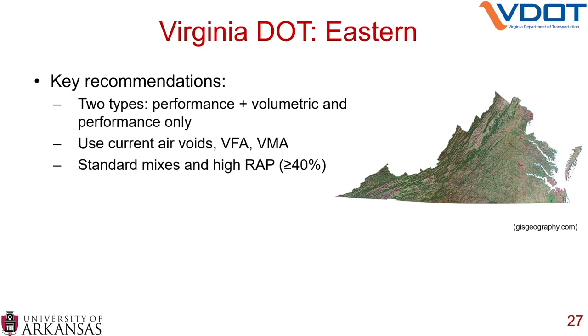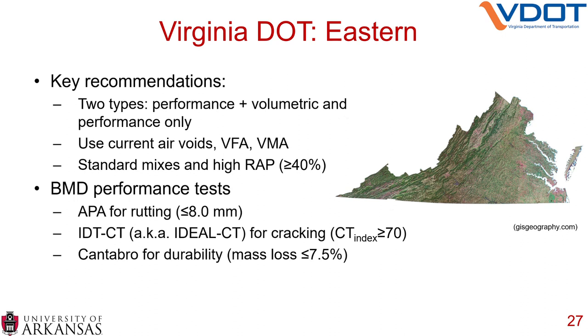They developed guidance for both standard mixtures, which essentially had low percentage of RAP, and mixtures that had high percentages of RAP, and they defined high RAP as greater than 40%. And then the balanced mix design performance tests that they recommended were the APA for rutting, the asphalt pavement analyzer, which is less than 8 millimeters. Now I apologize, they recommend the IDT-CT, and as far as I could tell, that's the same thing as the IDEAL-CT. I apologize to Virginia if you have some subtle differences, but they claim that CT index should be greater or equal to 70 for cracking using the IDEAL-CT as I read it.